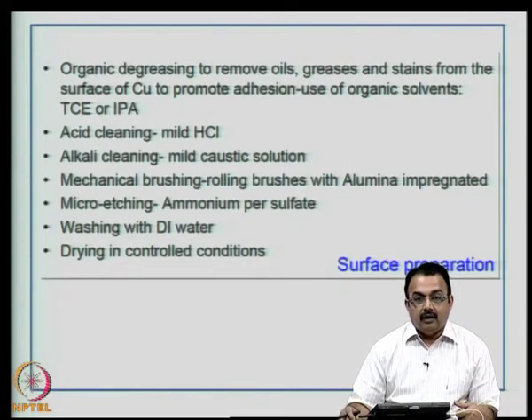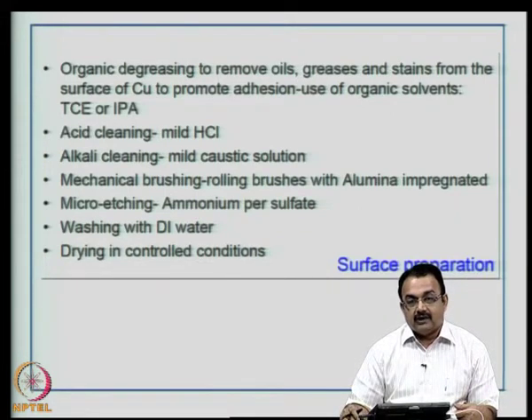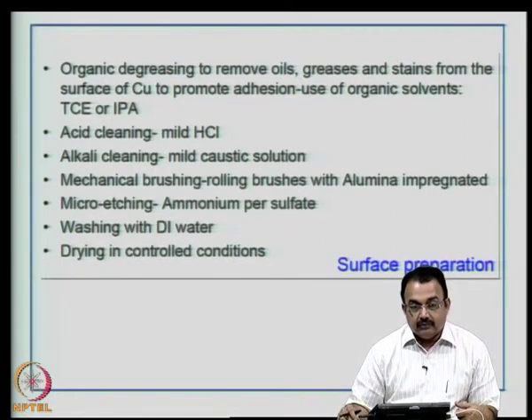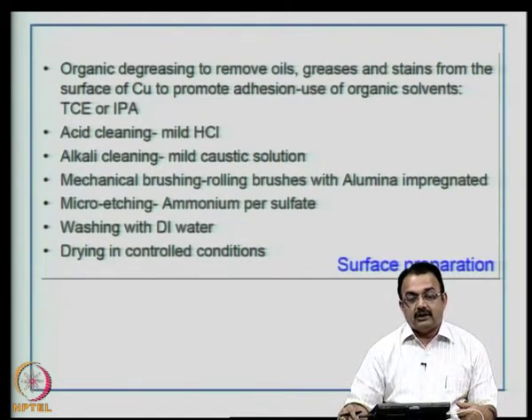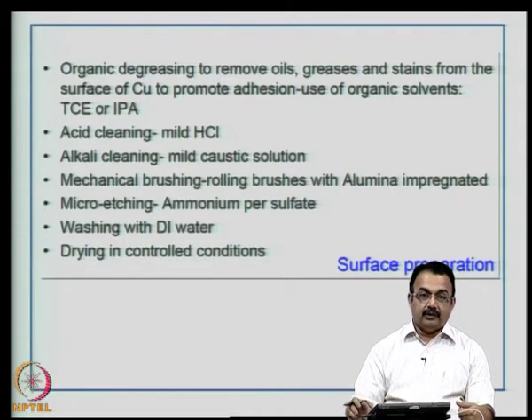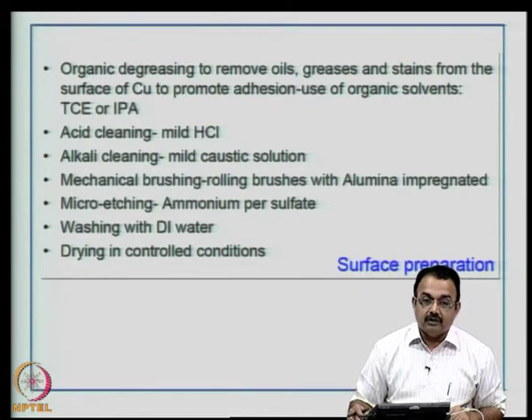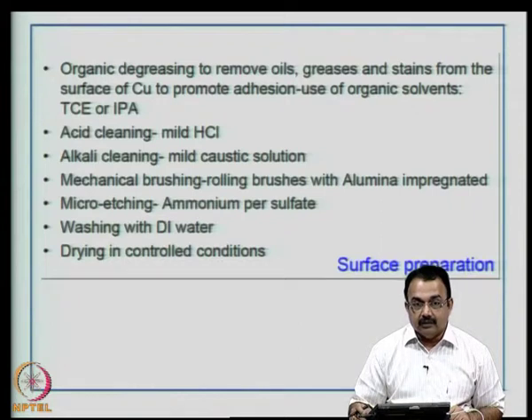Due to large storage, there can be accumulated particles, dust, and stains — copper is moderately reactive to atmosphere and can react with oxygen to form copper oxide. Oil, debris from equipment, greases, oxides, and other chemical stains can all affect the surface. Laminates need to be protected until used, but nevertheless the surface of copper must be treated. Treatment is required because we are going to promote adhesion on the surface of copper. We are going to transfer an image onto the copper surface using a photoresist material, which must adhere nicely onto the copper surface.